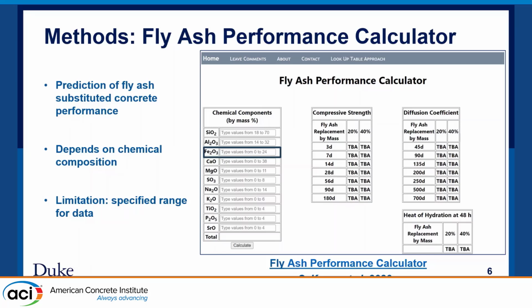As we walked through this method, we saw that there is a definite range for the chemical component percentages in the coal combustion ash. If we exceed these values, we couldn't get the result from this calculator. We saw that some components exceed these values, and it couldn't give us the result we wanted. So this can be a good opportunity to expand the study of this calculator as well.